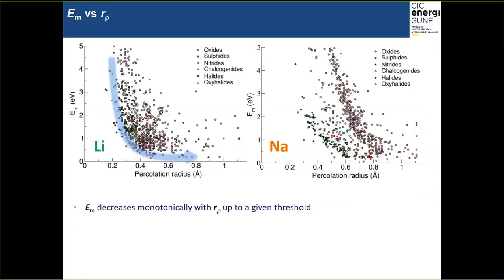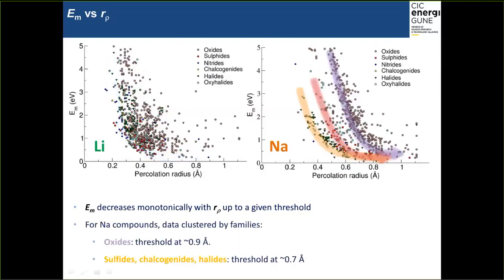So this makes the migration energy decrease monotonically with the percolation radius up to a given threshold, about 0.5 angstroms in the case of lithium compounds. For percolation radius greater than this threshold, there is no further substantial energy gain by enlarging the percolation radius, and therefore the migration energy stays constant. Furthermore, in the case of sodium compounds, the distribution of different families is clearer than in the case of lithium. For example, here the oxides show the highest threshold, whereas sulfides, chalcogenides, and halides have lower thresholds in general.